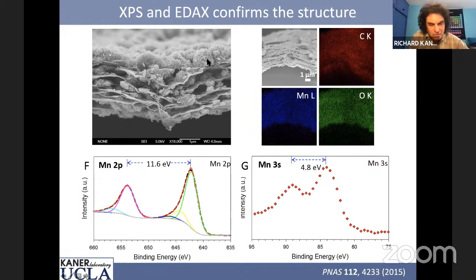And these things that sort of look like cauliflower-like structures, that is the manganese dioxide. And we can look by XPS and we can see that it's in the right oxidation state for the electrochemically active form of manganese dioxide. And then we can look using EDS, and we can see the carbon spread throughout, and the manganese and the oxygen. So basically we have a very nice distribution of manganese dioxide throughout this carbon lattice.